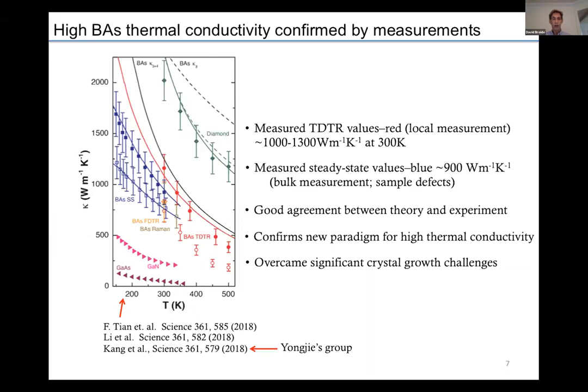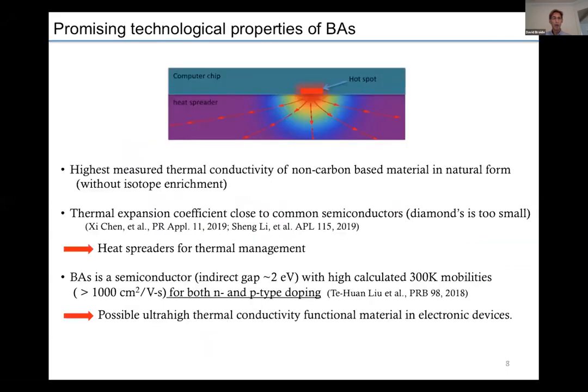So this agreement between theory and experiment then validates this new paradigm for achieving high thermal conductivity and identifies boron arsenide as a new unconventional ultra-high thermal conductivity material. So while the thermal conductivity is not as high as in diamond, boron arsenide does have some advantageous features.